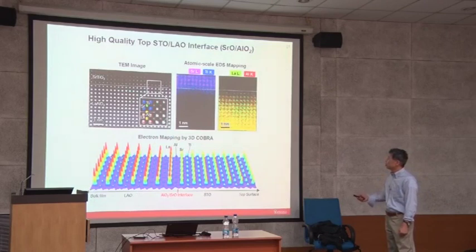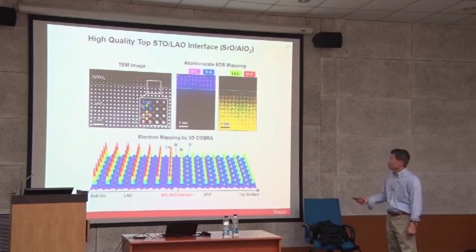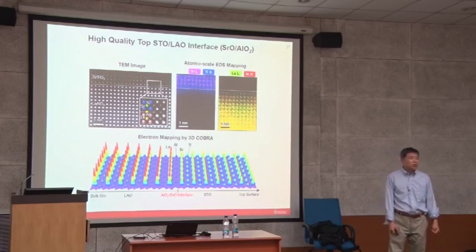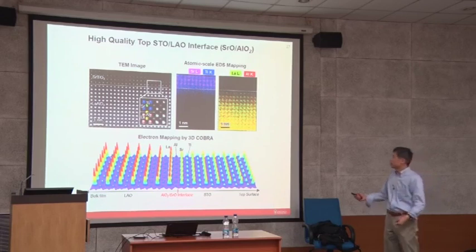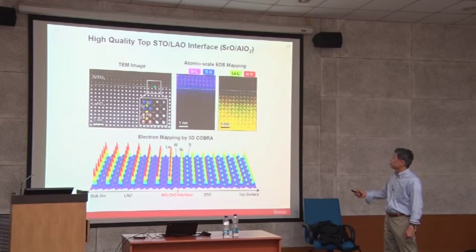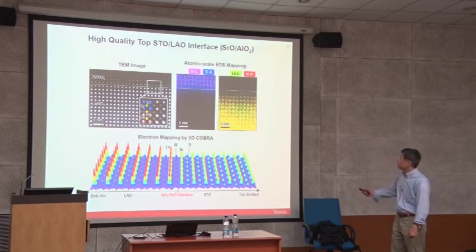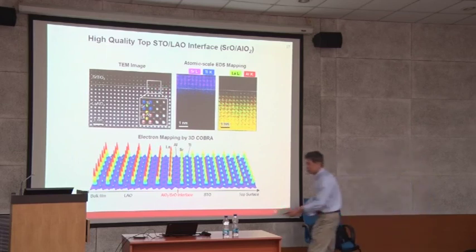both are STEM images, like a scanning transmission electron microscope image, where heavier atoms are brighter and lighter atoms are darker. It's a Z-contrast image. You can see here the interface regions: aluminum here, lanthanum, and this aluminum, and next one, strontium and titanium. You can see that.